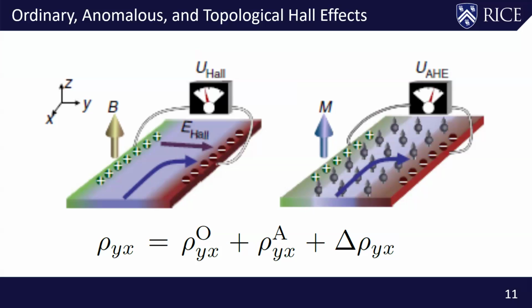And this is what we typically contribute as an anomalous Hall effect. Of course, if the system is not a simple pure metal but a magnetic metal, which has an intrinsic internal field applied on the system by itself through the magnetic ion, you would have this sort of anomalous Hall effect, which should be there even when the external field is reduced to zero.